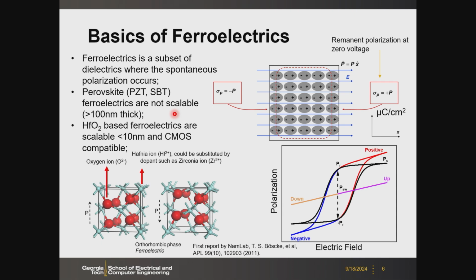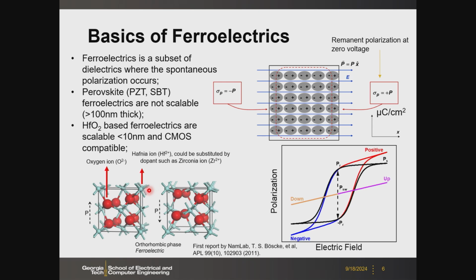So about 13 years ago, there was a first report from the NaMLab from Germany. So the hafnium oxide system could show the ferroelectricity if it's properly doped with certain dopants to create this so-called orthorhombic phase. So depending on the crystal orientation, then you may have the built-in dipoles with those 2 possible configurations. And therefore, you can have this ferroelectricity in the hafnium oxide system.